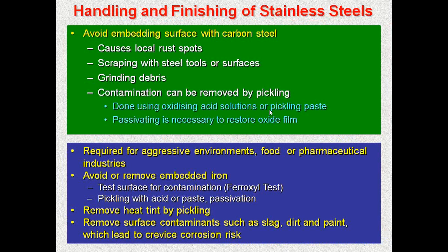If you want to handle and properly use stainless steels, you have to be careful of the following points. You have to avoid embedding surfaces with carbon steel. Normally people manufacture stainless steel components in a workshop where carbon steel is also fabricated, and they don't realize this. Carbon steel is a very hard component which will get embedded in the soft matrix of stainless steel, and it will cause local rust spots, and scraping with steel tools also causes such things. Grinding debris attached to the surface we have to remove by pickling treatment.